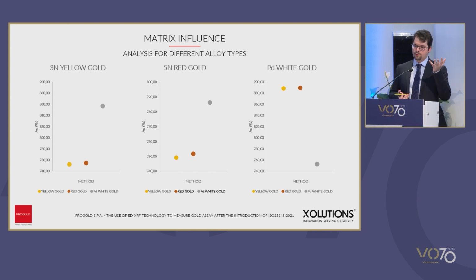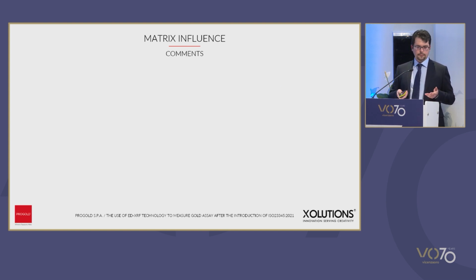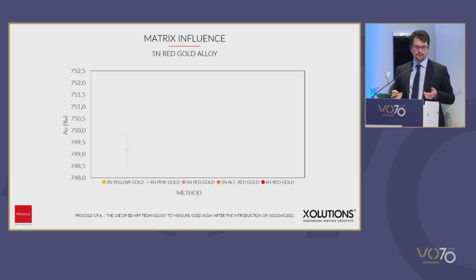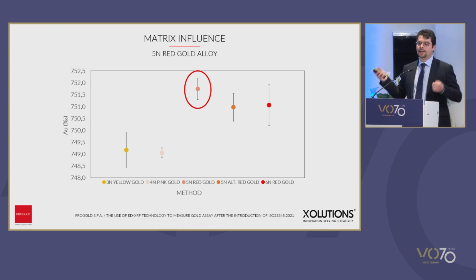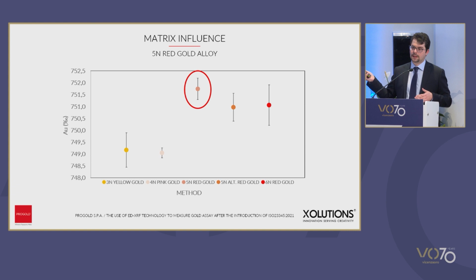we shouldn't use methods for different colors, but if we concentrate on just one color, so let's take our red alloy, and instead of analyzing it with its specific method, we can use methods for other red gold alloys with a higher copper percentage. And this is the result that we achieve. Above, you see the original measure, the calibrated method. It's in the red circle. And below, you see the results achieved by other methods.